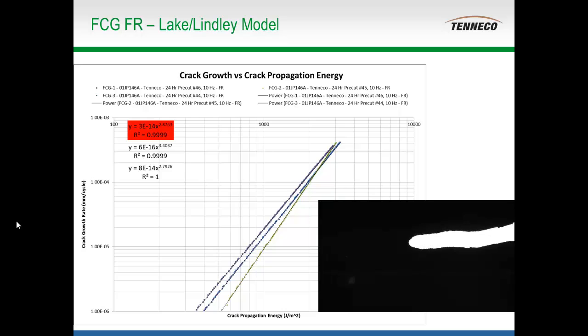I show the actual data used in the correlation, although I'm going to stay on this slide for a second so everybody can watch this at least twice. Basically, on the y-axis is the crack growth rate from 1e-6 up to almost 1e-3 millimeters per cycle, versus, internally, we like to think of it as the crack propagation energy. That helps us explain it to some of our product designers a little bit easier versus continuing to refer to it as the unloading energy or the maximum unloading energy.